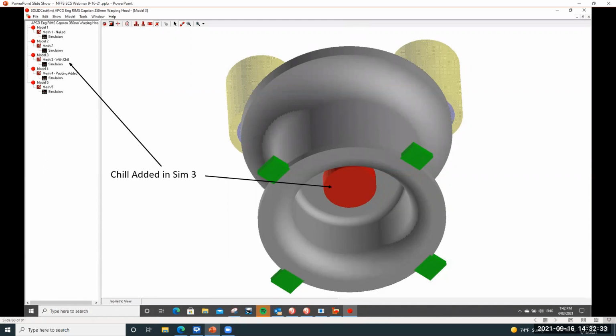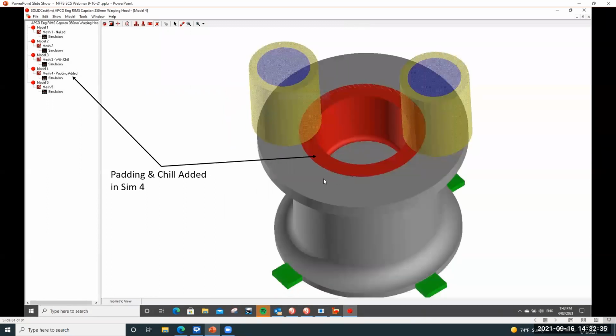That saves us time, but it also gives us a good idea of what's happening with the filling process or the effects of the filling process. After putting in that chill, we still weren't getting complete progression of solidification through. So we actually made an adjustment to the casting geometry by adding a circular pad on the inside, again, doing simplified filling. And we were able to then verify that the risers could then feed through and completely feed the